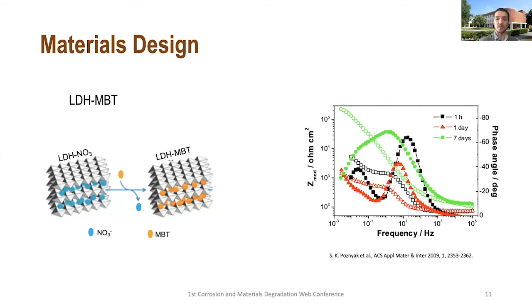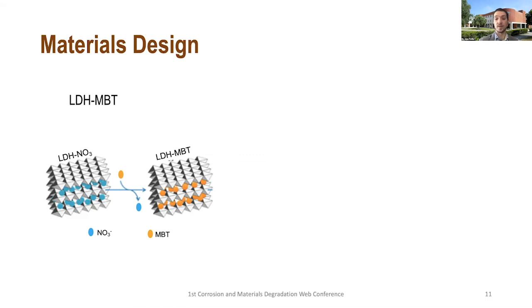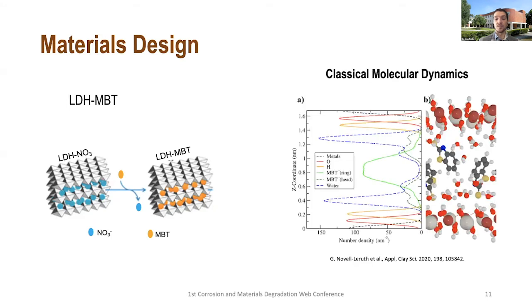However, in spite of the fact that we are able to characterize and see the expansion of the basal spacing, so the distance between the layers, when there is an accommodation of the corrosion inhibitor, so there is a structural proof that the compound is intercalated, and then later we see by release studies that it is released, it's necessary to also have additional understanding on how the inhibitor is there, and how to basically have the possibility to have the molecule organized and the water molecules there as well.